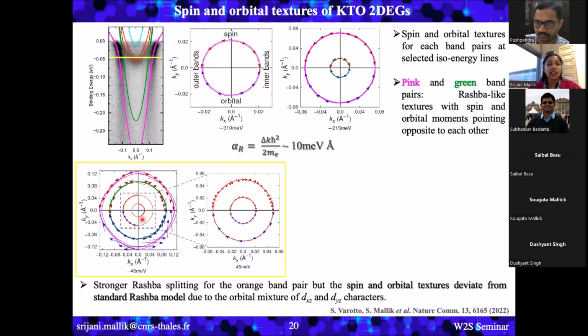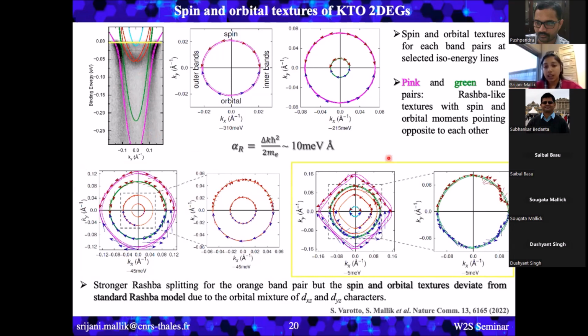So there is a huge compensation effect, and the length of the spins here are basically telling you about the spin expectation values. So in this case, for the highly Rashba split bands, we can see that the spin expectation values are really small. So this also indicates that the spin Edelstein effect should not be very large from this kind of samples. And as we move further to higher energy, we can see that the model completely deviates from the standard Rashba model, and very high hybridization starts appearing in the band structure.